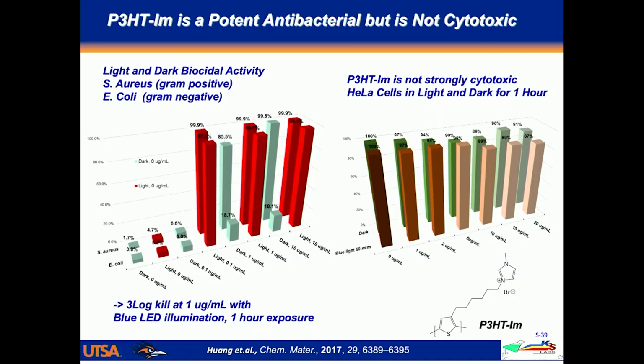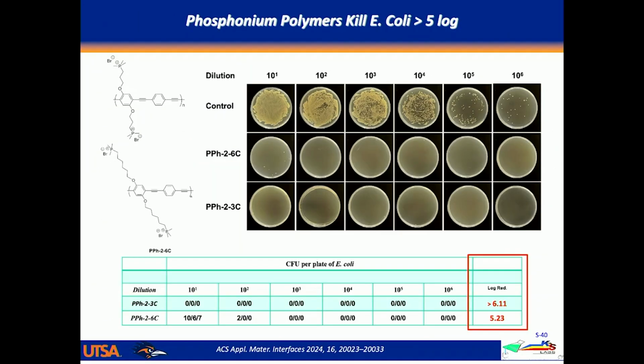So this polymer is, in weight amount, essentially 100 times more effective, but of course you have to add light as well to activate it. I mentioned also a size work with these phosphonium polyelectrolytes. These are also pretty effective at killing. In the case of these guys, this work is done at 20 micromolar concentration, so it's higher than the polythiophene, but now we're up to almost 6 log kills.